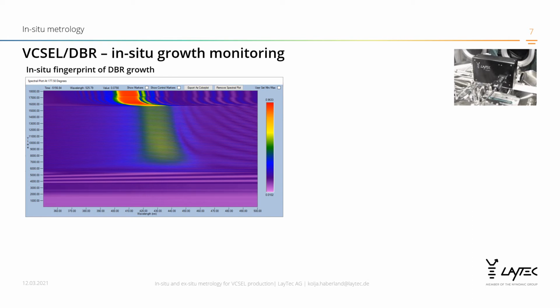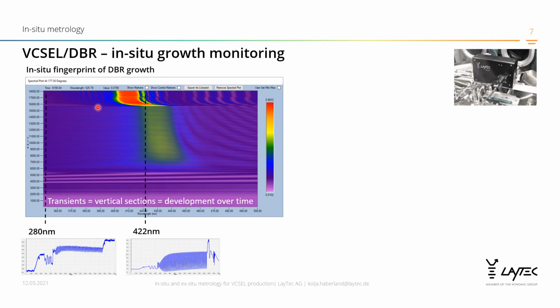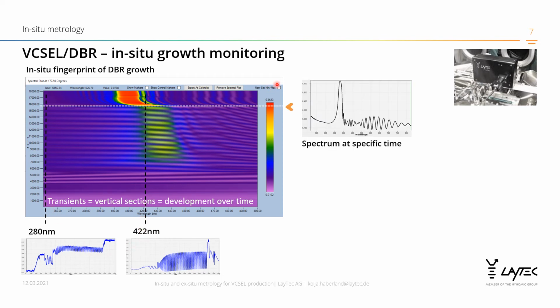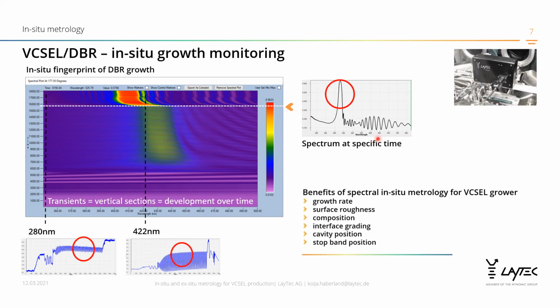Here's a real-life example of the in-situ fingerprint of a VCSEL or DBR structure growth. We see here the reflectance signal coded in colors, and we can extract the behavior of the reflectance at certain wavelengths over time. And we can also extract spectra taken at a specific time, showing us the whole reflectance in the visual, infrared, and UV range. Analysis can provide growth rate, surface roughness, composition, interface grading, cavity position, and stop-band position, and is very valuable for understanding the growth.